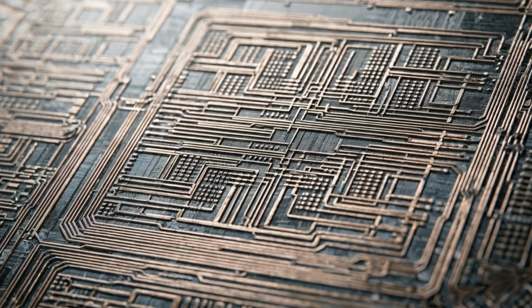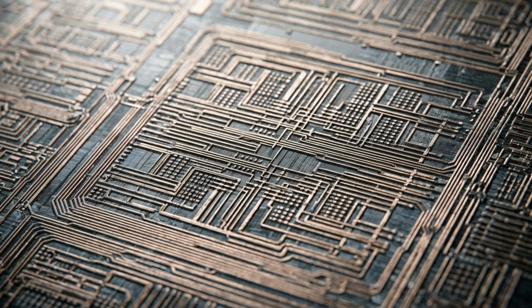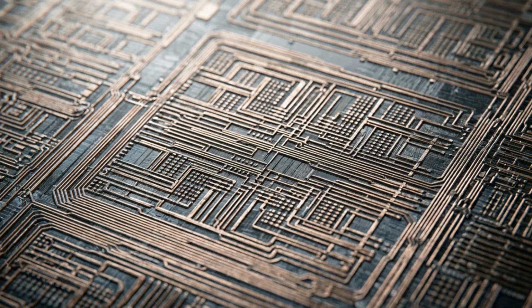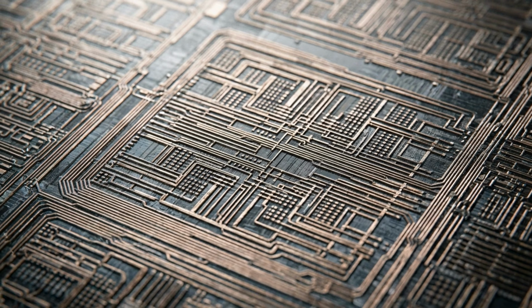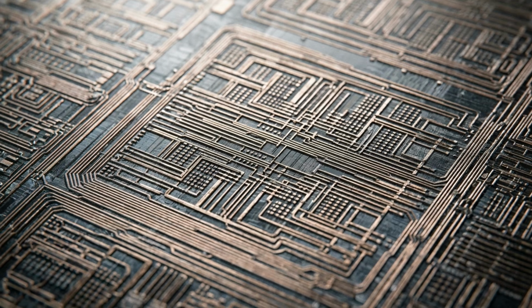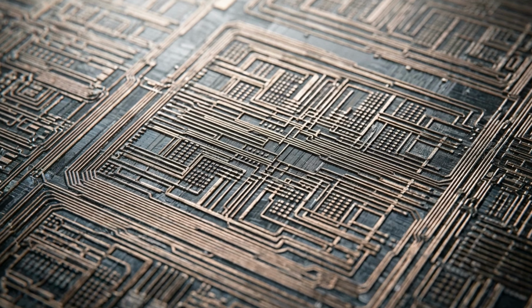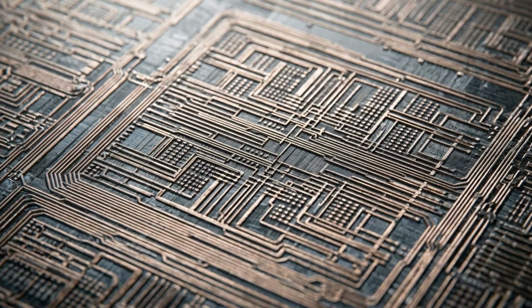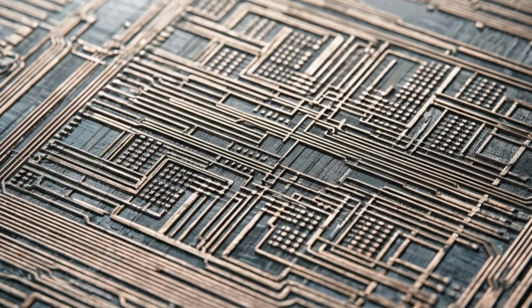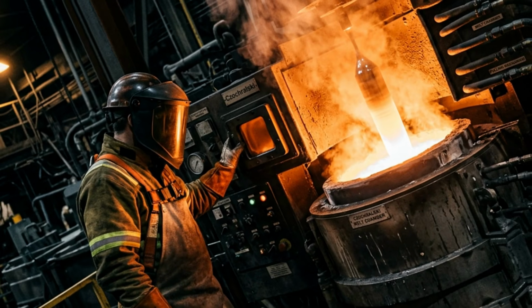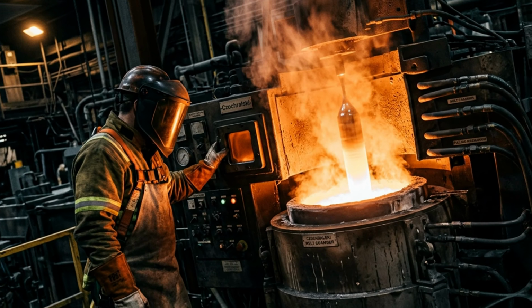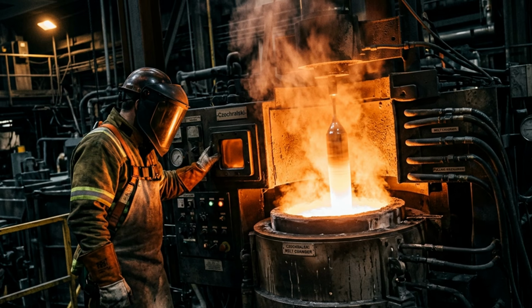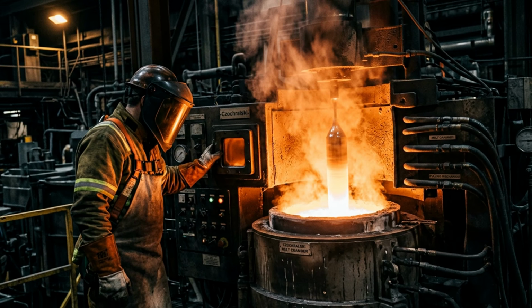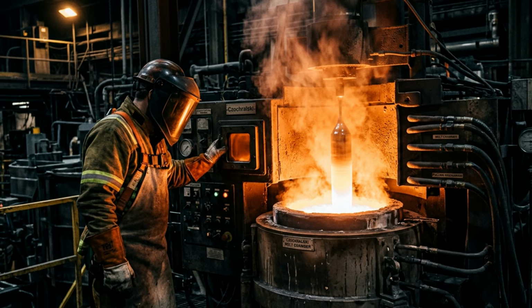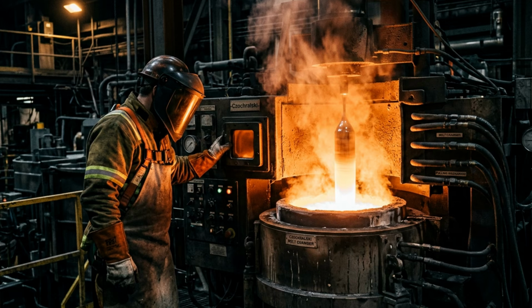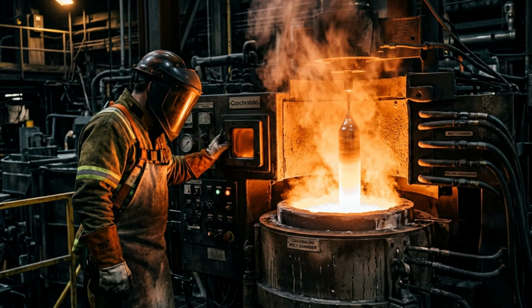To achieve this, raw silica rock is mined primarily in regions of the United States, Brazil, and Australia. It's then processed through a series of chemical reactions that strip away every impurity. The result is a dense, silvery material called polysilicon, which is then melted down at temperatures exceeding 1,400 degrees Celsius inside a quartz crucible. Here, a single seed crystal of pure silicon is dipped into the molten material and slowly rotated and withdrawn over dozens of hours. The result is a perfect silicon cylinder called an ingot, sometimes nearly 2 meters tall and weighing over 100 kilograms. From the outside, it looks like a large metallic sausage, but inside, it is a flawless crystalline structure aligned at the atomic level. Every atom precisely in place, every defect essentially zero.